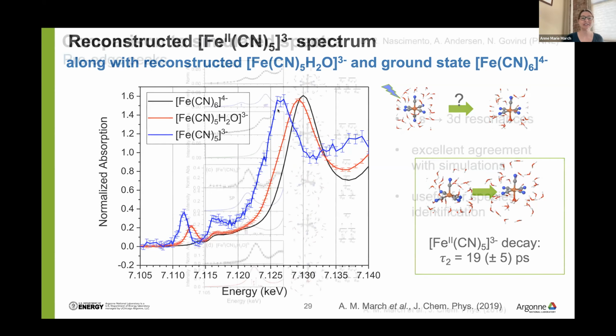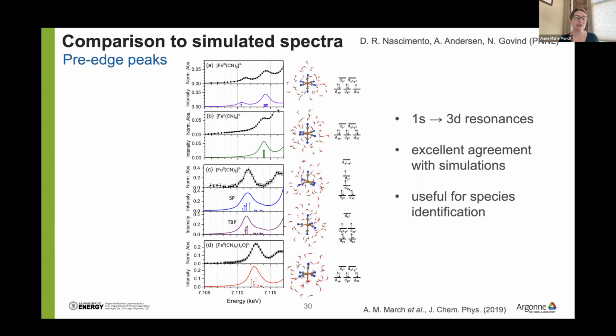Okay, so then we turn to our theory colleagues, collaborators, to say, does this make any sense? And so this is Niranjan Govind, Aaron Andersen, and their postdoc, Daniel Nascimento, did some calculations for us. They did TD-DFT simulations of the pre-edge region. So the pre-edge region is particularly informative because the resonance is from 1s to 3d, and it can tell us about the geometry of the species, which helps us identify what we've got.